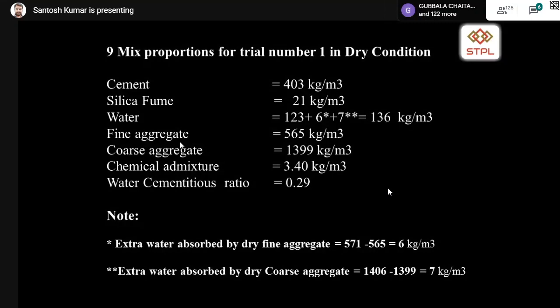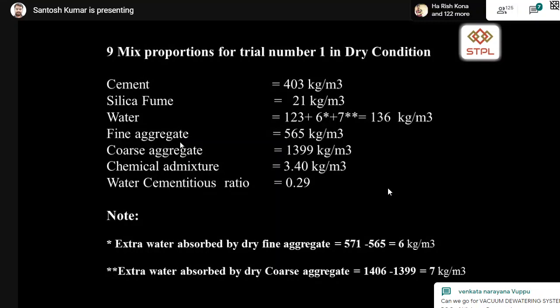In the same case, fine aggregate 6 kg you have to reduce, and the same 6 kg you add in the water content. In the same case of coarse aggregates, 7 kg you reduce in the weight and you add in the water content. That becomes your mix proportions as per dry condition.